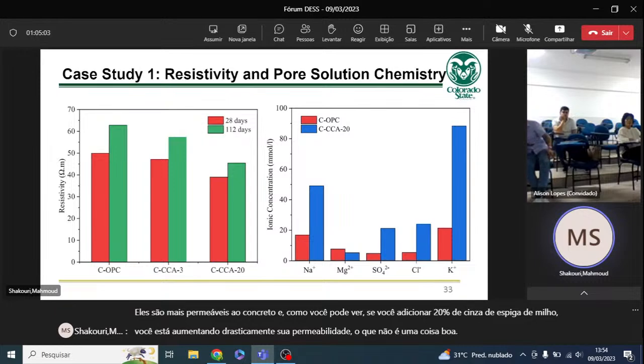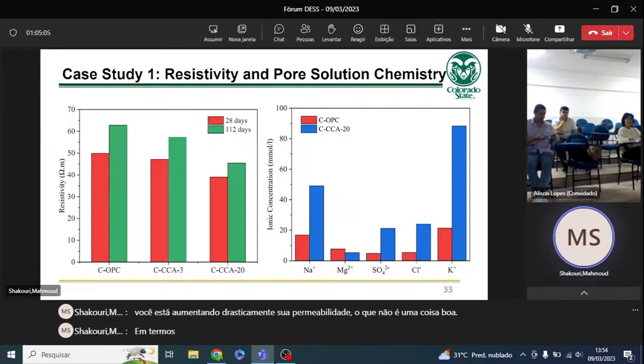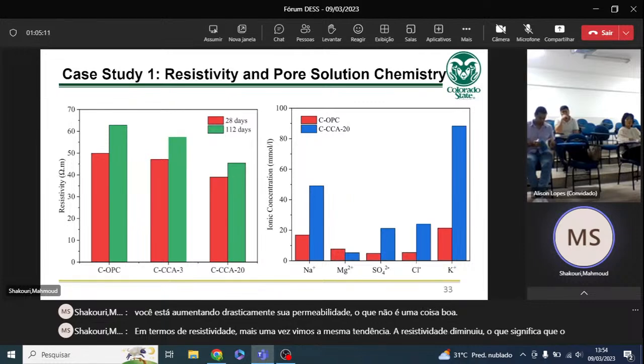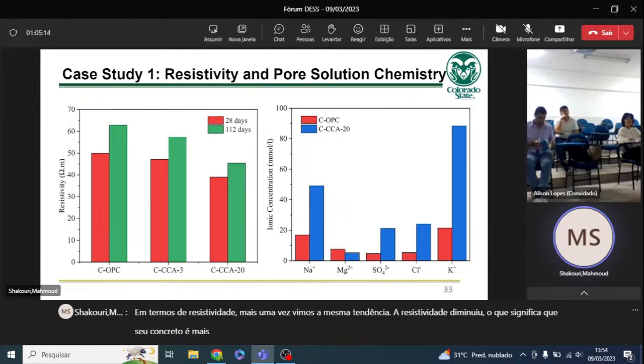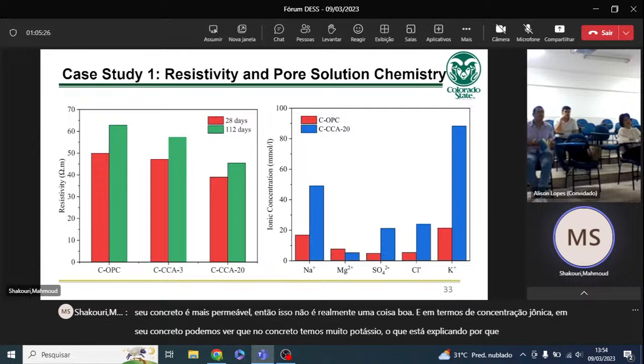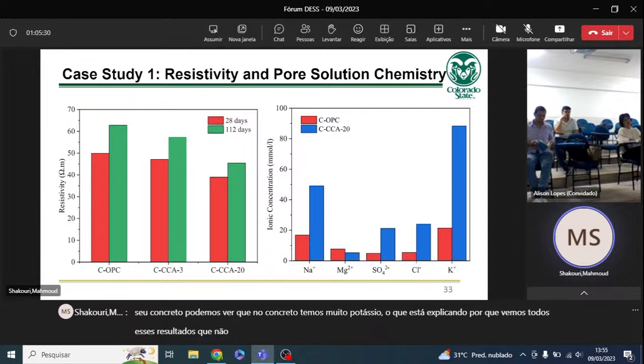In terms of resistivity, again, we kind of saw the same trend. The resistivity went down, meaning that your concrete is more permeable. So that's not really a good thing. And then in terms of ionic concentration in your concrete, we can see that we had a lot of potassium, which is explaining why we see all of these results. We didn't get good strength, we didn't get good permeability.